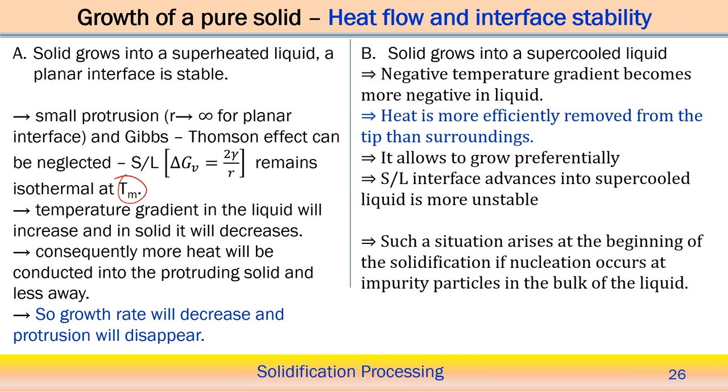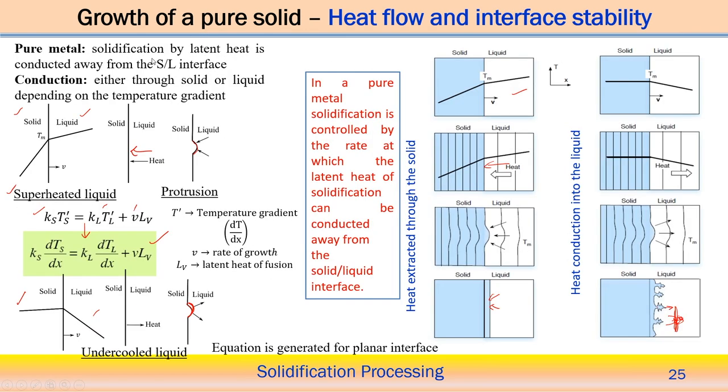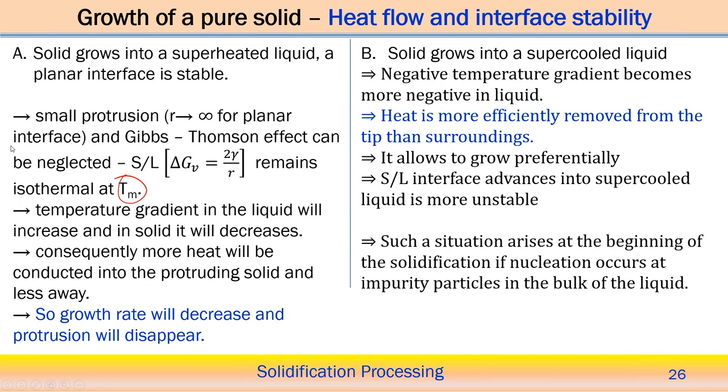Now the temperature gradient in the liquid will increase and in the solid it will decrease due to heat transfer. When heat is extracted from the liquid phase to the solid phase, the temperature gradient in the liquid phase gradually increases and in the solid it decreases. Consequently, more heat will be conducted into the bump, that means the protruding solid, and less heat into the surroundings. So growth rate will decrease, and gradually this bump will disappear,